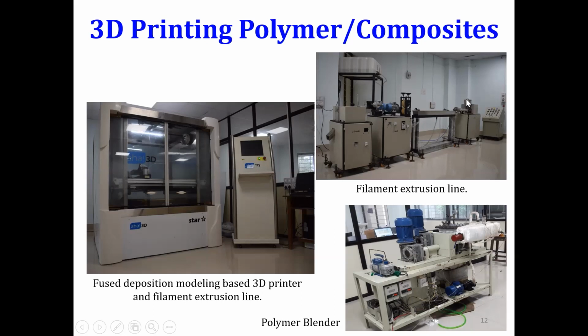If you don't have it, then these entrapments go into the filament, and in 3D printing, these voids will creep in. Though it is a downside, please do remember that though we have the air entrapments in the filament, which get transferred to the 3D printed final component as well, if those are uniformly distributed, I repeat, if the defects or the voids are uniformly distributed, there is nothing to worry about.